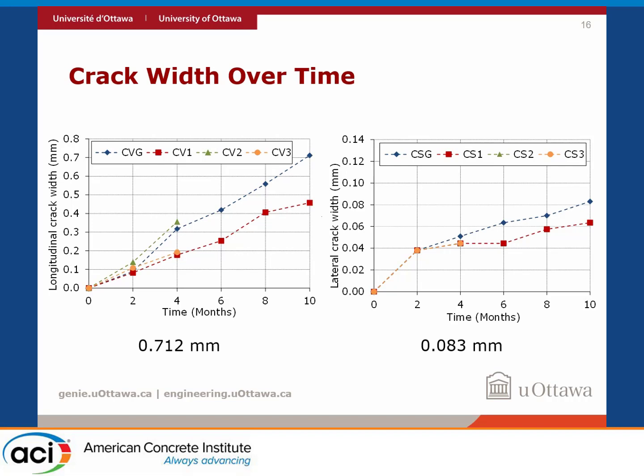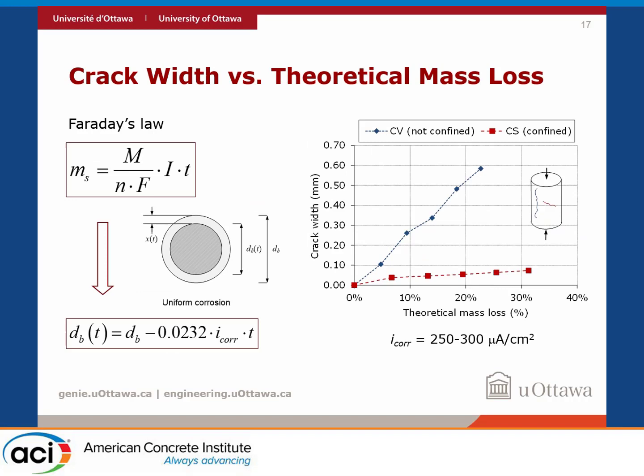We calculated the theoretical mass loss over the period of time that they were tested based on Faraday's law. One of the problems is that Faraday's law assumes that the entire current is being used for corrosion, with no losses. Based on that, we could clearly see that there was an increase of crack width with mass loss. And obviously for the CS specimens, the ones with just the spiral reinforcement corroded, the crack width was much smaller, which we believe is the effect of the sustained loading.